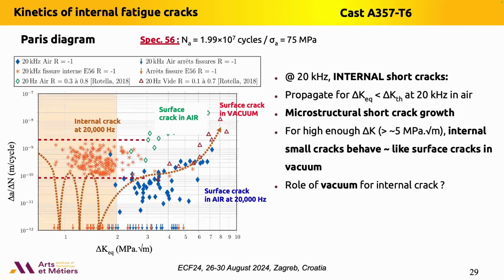So we have obtained the following results plotted in the Paris diagram. There are many things plotted in this figure, so I will take a few minutes to explain. Our results are in orange. Our results are the internal cracks at 20 kilohertz. These are the orange stars. First, all these points correspond to the crack advance all around the crack front after different instants of the loading. When the crack is small, the cracks oscillate between propagating at a low speed and arrested, like a classical small crack at the surface that is interacting with the microstructure.